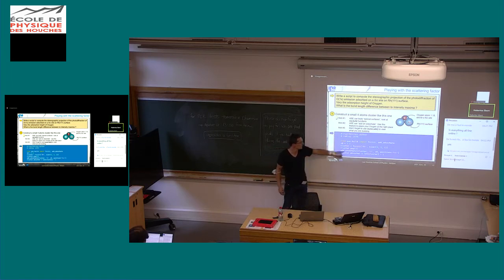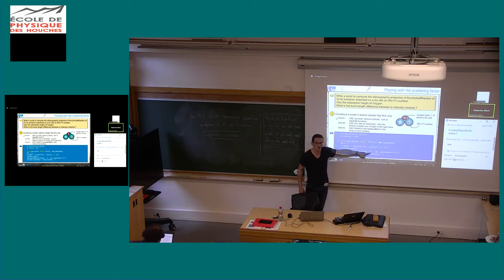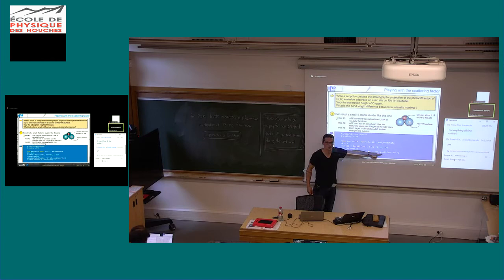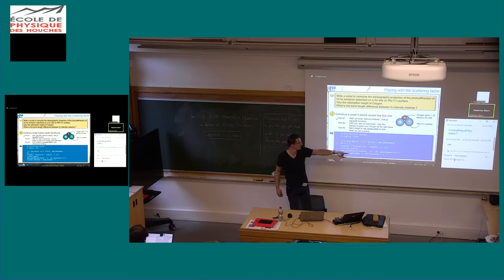And then you use the add_adsorbate function. You must specify the host, so this is the cluster, and which kind of atoms object you will put on this site. It may be an atoms object, but it may also be a string, so here an oxygen atom, the height of adsorption, and the position. For a known surface, you just have to specify the name of the adsorption site. For rhodium, I guess there are the FCC and the HCP sites, two sites known to the function.